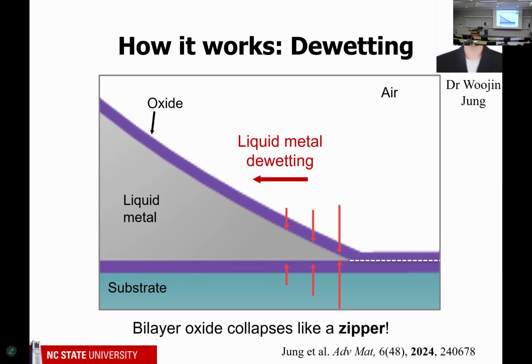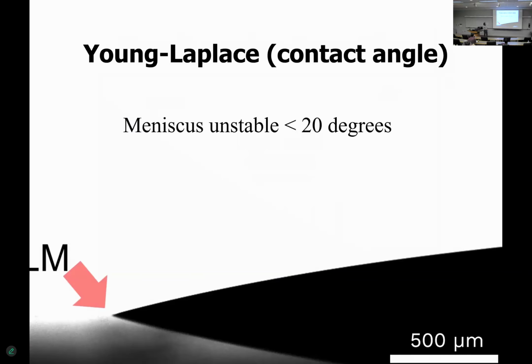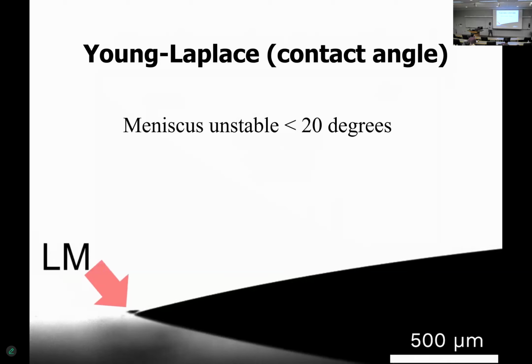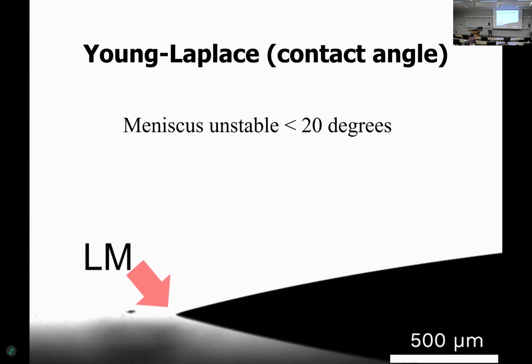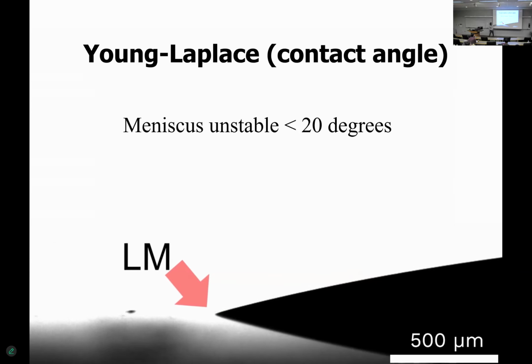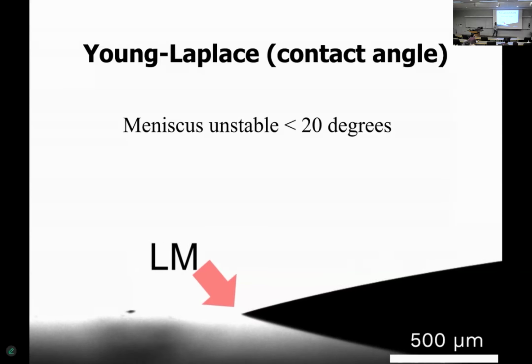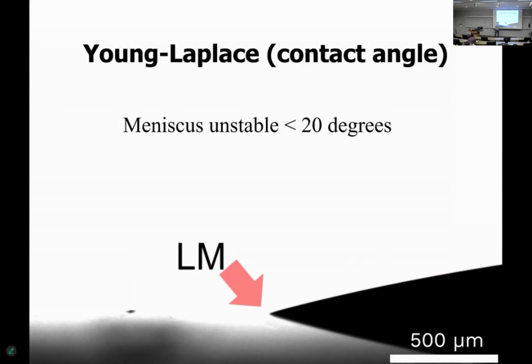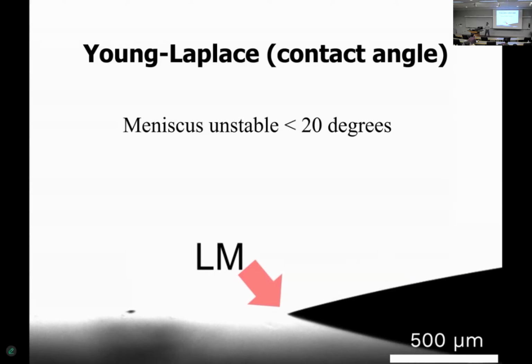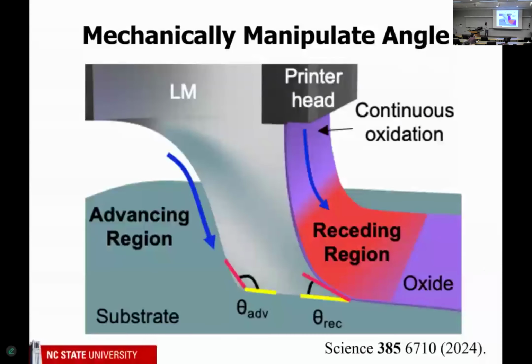So in the previous video, the liquid drained due to gravity, but I can show you where we've done this even on flat surfaces. This black thing is the liquid metal, and you're seeing a reflection of it. So it's actually just a meniscus, and you're seeing the reflection. But anyway, after we've made this thing unstable, you'll see that it will collapse, and you can't see it because it's so thin, but this is the oxide. So it's just leaving a beautiful layer of oxide. And so there's even a kind of better way to do this.